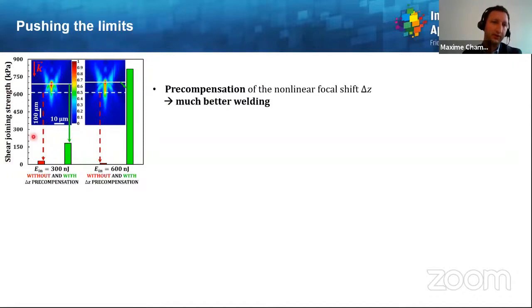Well, to answer this, here I represent the shear joining strength between the silicon and copper for 2 input pulse energies, without in red and with in green precompensation of the nonlinear focal shift. And the striking feature from this figure is that precompensating the nonlinear focal shift leads to a much better welding. Okay, so now the main question is, can we simultaneously keep this precompensation of the nonlinear focal shift delta Z strategy and increase the input pulse energy to get even more energy deposition at the focus?